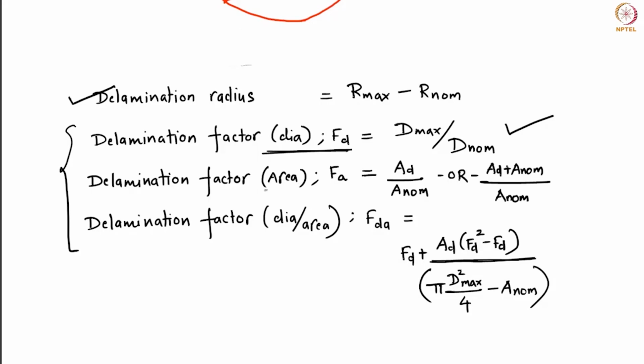Okay, you can also calculate this based on the area. Here you will take the AD, the area of the region that is actually delaminated, divided by the nominal area, and in most cases this is the one that gives you very accurate values, because here you're not calculating, as I said, the bigger circle. It might be that only one strand or one yarn of the fiber was damaged for a large distance, but the other fibers did not damage at all. So diameter may not give you the best idea of what is happening, but area may give you the exact values. But at the same time, it's more difficult to calculate the area compared to the diameter.